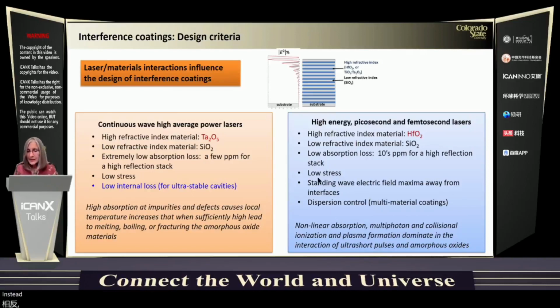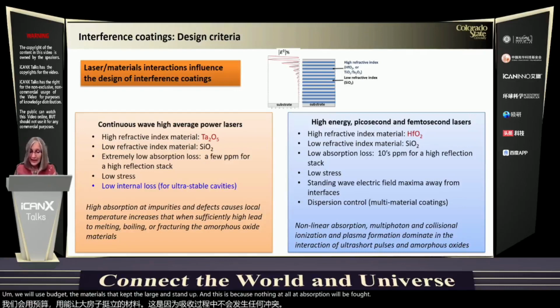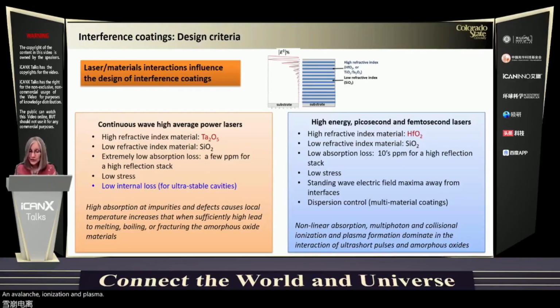Instead, when we design interference coatings for high energy picosecond and femtosecond lasers, we will use the materials that have the largest bandgap. And this is because nonlinear absorption, multiphoton, and avalanche ionization and plasma formation dominate in the interaction of ultra-short pulses and the materials. Again, here we are going to strive to have low absorption loss, but it's not required to have ultra-low absorption loss. 10 parts per million is sufficient.